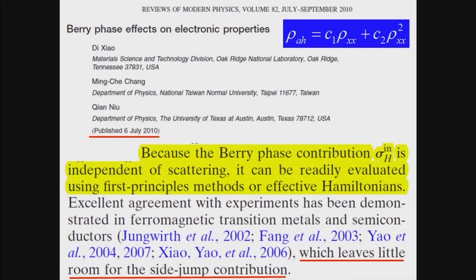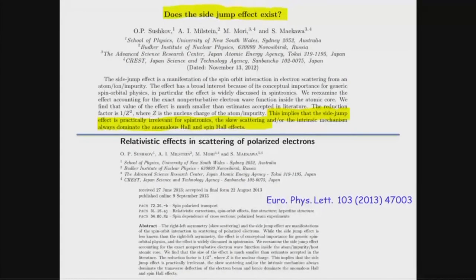Another paper in the same year, 2010, the Reviews of Modern Physics by Qian Niu and his collaborators, also strongly favors the intrinsic mechanism, and more explicitly says this leaves little room for side jump. And there's another paper by Sadamichi Maekawa and his collaborators in 2013, whose abstract clearly says that side jump, even if it exists, is irrelevant for spintronics. Only the intrinsic one is important. So you see, this is a kind of controversy. After Edwin Hall found this effect 130 years ago, people are still arguing about which mechanism is more important. So that's our contribution.